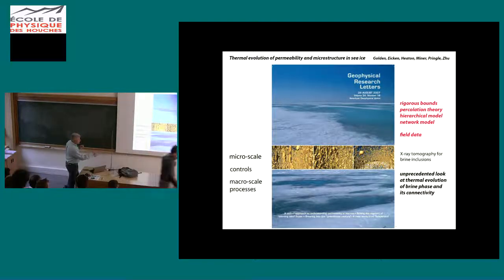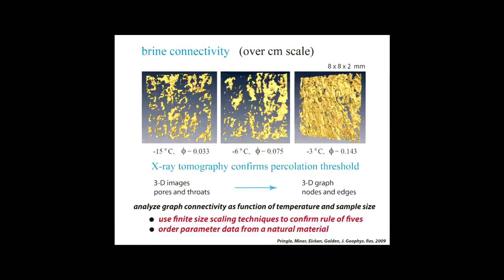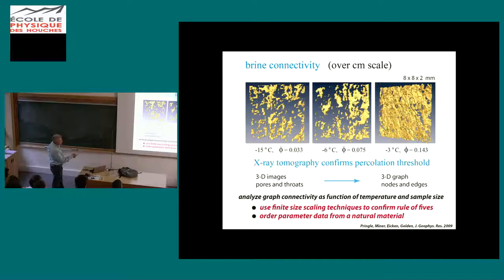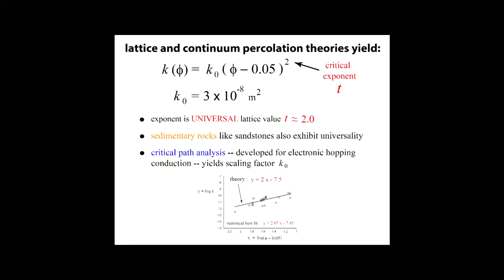What was important about this X-ray tomography is that we could finally start to confirm this rule of fives, that there really is a percolation threshold at this critical brine volume fraction. Here's some of our X-ray tomography: no pathways, one pathway, many pathways. We map 3D images of pores and throats onto 3D graphs of nodes and edges and use so-called finite size scaling techniques in physics to confirm this rule of five and get our hands on the percolation threshold.